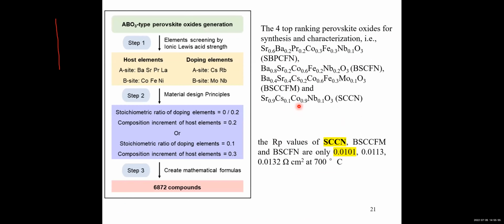We actually fabricated these materials, especially this one, SCCN for short. We tested the performance of this material and found the polarization resistance is really very low, at 700 degrees Celsius it's only 0.0101.